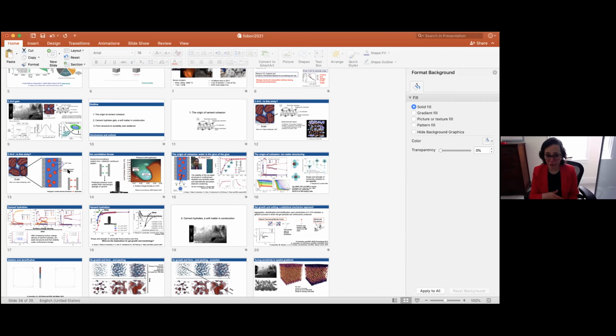However, once we had done the simulations, we were able to compare our results with what people see in atomistic simulations, where they basically look only at the situation where you have the highest confinement. The surfaces are very close, so very few water molecules are left. And if we go back, we can see that the water structure, the amount of water, the coordination of water and of the ions that we get in those conditions is in very good agreement with what is obtained with these atomistic simulations for the highest surface charge. So this suggests that we have taken a very strong approximation, but it's not too bad for the moment.